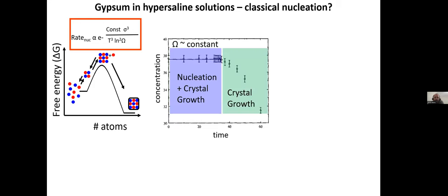Now, I've also shown you this graph you see here. And during the time where nucleation dominates the system, I also have that there is no change in the chemical composition. That tells me that nucleation occurs dominantly under a fixed oversaturation. So if I look at the equation on the left, also the oversaturation would be constant. So this tells me that every delta T during the phase of nucleation, I create the same amount of crystals that they grow in the same solution, so they should grow in the same rate.